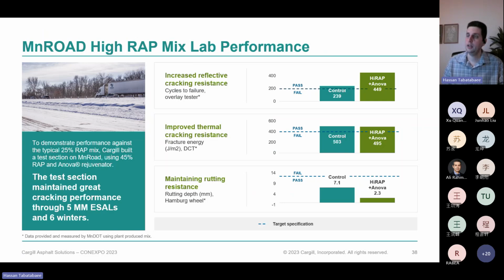Another example was done in a much cooler region. This is close to where our lab is in Minnesota. And again, this was designed for low temperature cracking resistance, 45% RAP. So performance testing showed that performance was equivalent or better. However, the important thing is after 5 million ESALs of this real traffic that's going on.